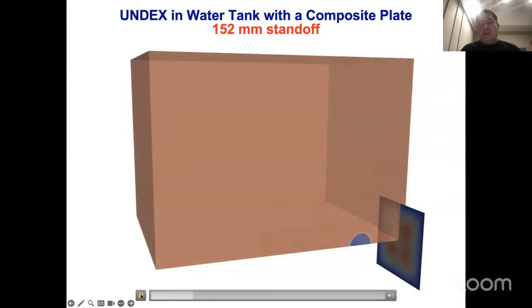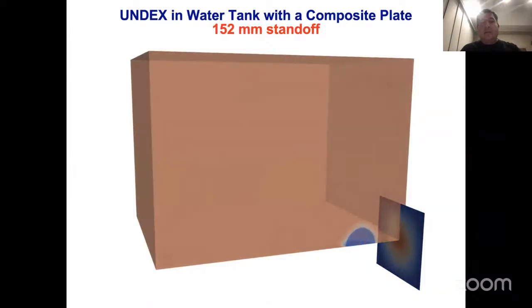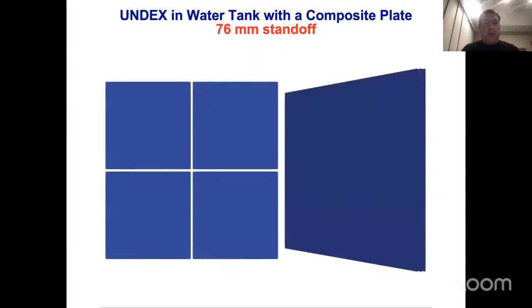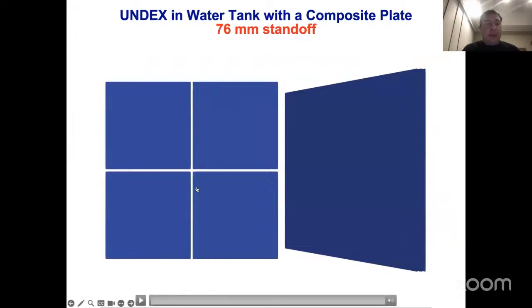That's a standoff at twice the distance, 152 millimeters, right? Again, you can see the fluid mechanics, the explosive bubble, and the structure interacting in a very dynamic way, okay? So that composite plate actually had 4 layers, so 4 that are shown here, and 3 cohesive interfaces, right? And what I'll show you is a movie that shows the time history of cohesive damage here, right?